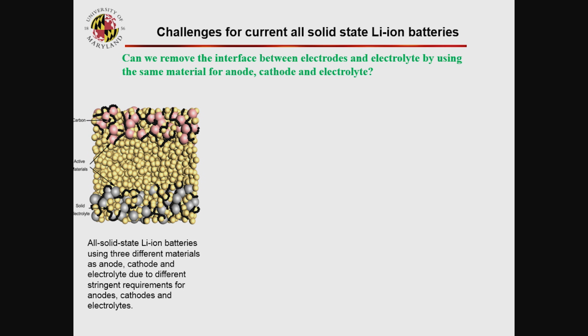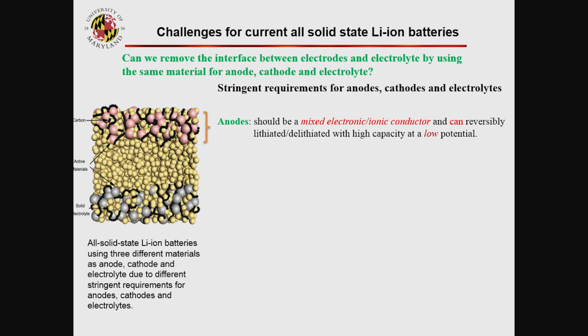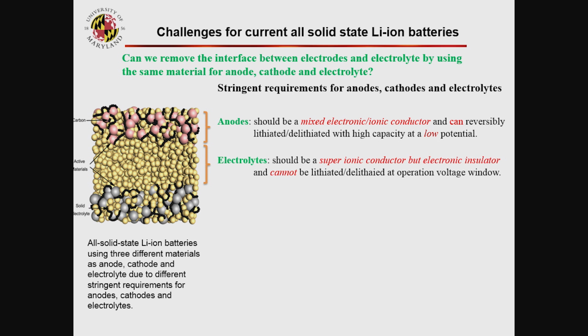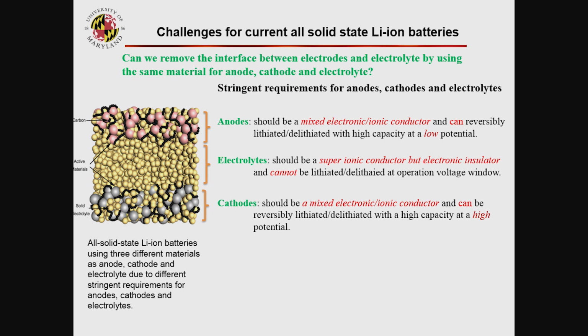In the technology right now, for the anode or cathode electrode, there are three phases. One is electrolyte, one is electrode, one is carbon black, because we need a mixed conductor. So now we ask, is it possible to use one material? Then we check the requirements. The requirement for the anode is that it should be a mixed conductor. You need to add carbon, or the material is intrinsically a mixed conductor. The second is that you have to have a high capacity at low potential. For electrolytes, the material should not react with lithium and should have no electronic conductivity. For the cathode, you should have a mixed conductor, high capacity, and high lithiation-delithiation potential.